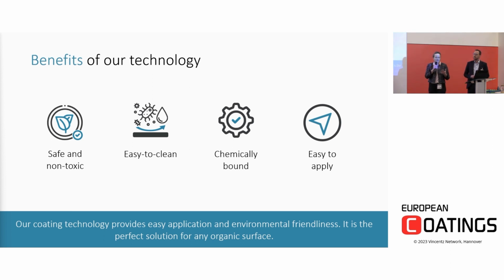The coating is actually not a coating. It's rather a surface functionalization. We bind our hydrophilic polymer via a UV reaction to the surface, so it's chemically bound, and thus very permanent, depending though on your main material. If your main material is very soft, our coating will be rubbed off as well, because the coating is very, very thin. It's only 10 nanometers. But if you have a very scratch-resistant plastic surface, our coating will stay with your material.